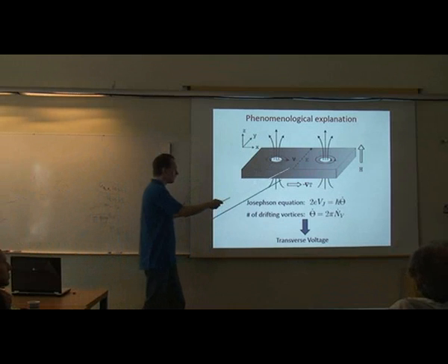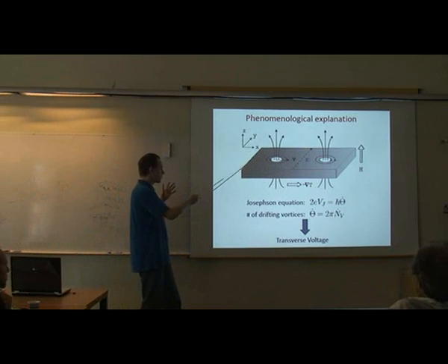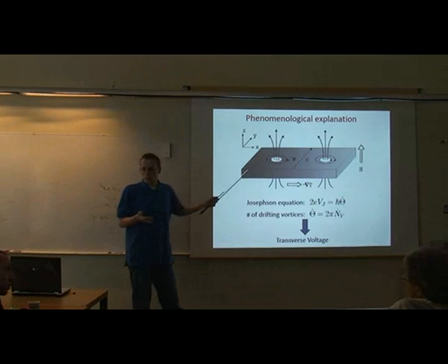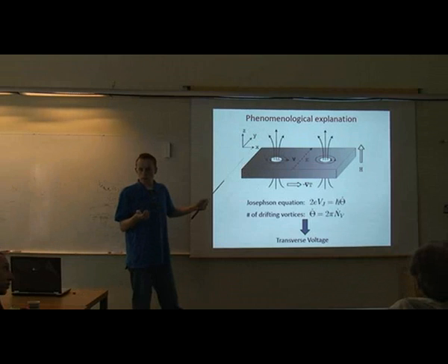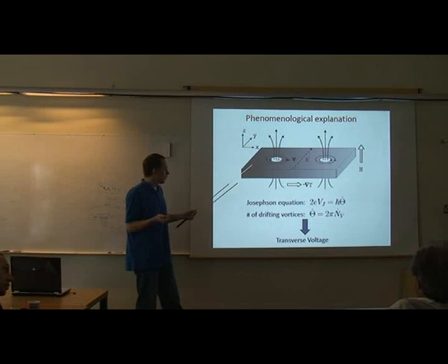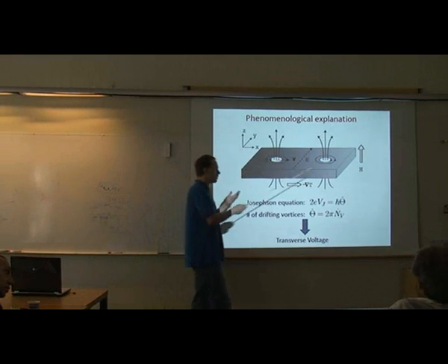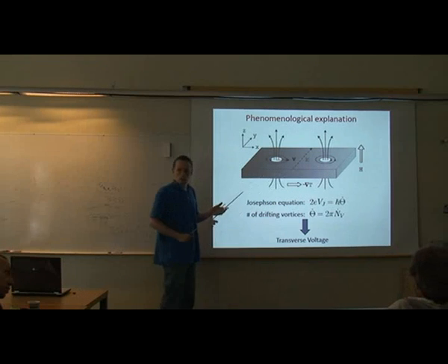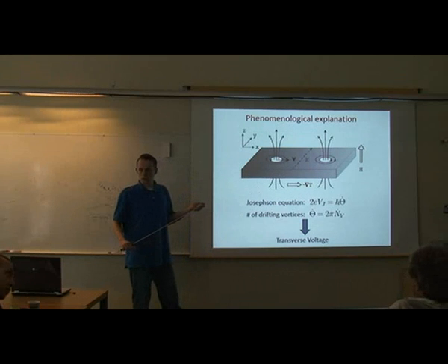It's rather phenomenological, and clearly there's no precise microscopic theory relating microscopic parameters to the Nernst signal. If you have the same number of vortices and anti-vortices, the Nernst signal will be zero, right? And you have non-zero magnetic field. Right, in zero field you generally wouldn't prefer vortices over anti-vortices. Yes, you definitely need the strong magnetic field. The Nernst effect is odd in magnetic field. So the previous slide was at finite field. It's all finite magnetic fields, finite thermal gradients.